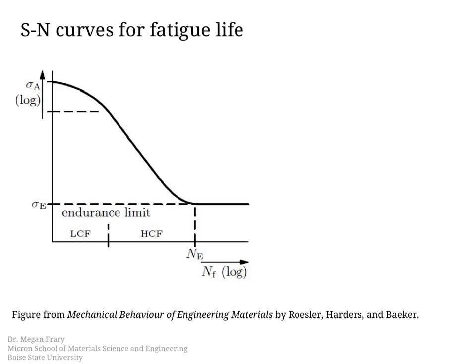And we notice here the endurance limit, or this is what I called before the fatigue limit. If there is not an endurance limit for a material or that's specified, then 10 to the 7 cycles is what's used. Another important thing to note on here is these two different regions of behavior which are marked out here.